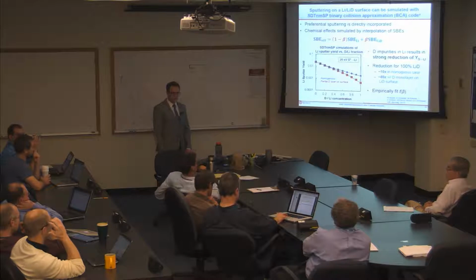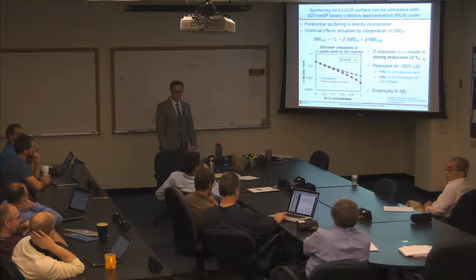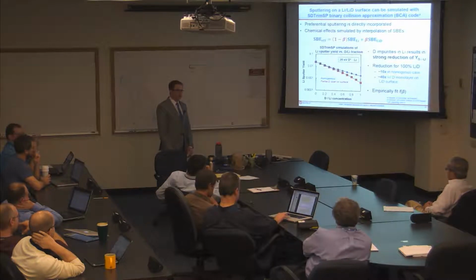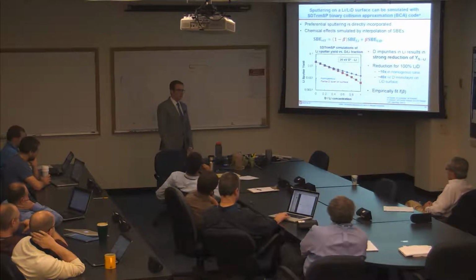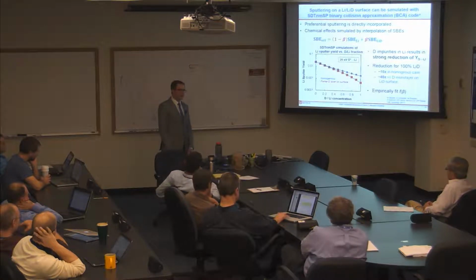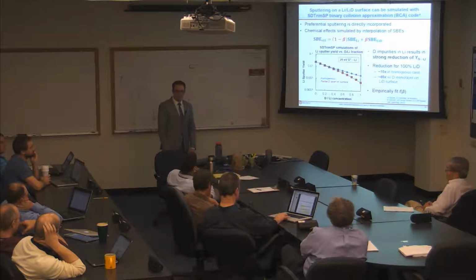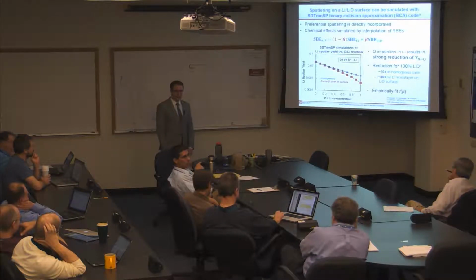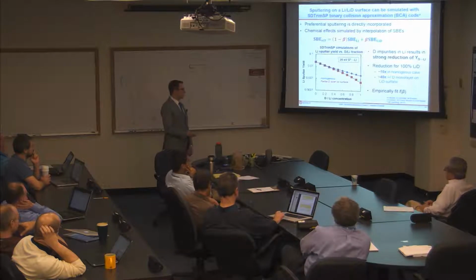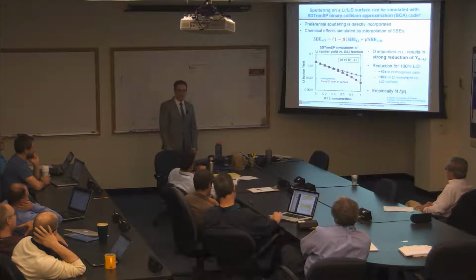You could have more D than that. But beta is 2. So in PISCES experiments, they found that the maximum deuterium concentration they ever saw retained in a liquid was 1-to-1. And they did thermal desorption spectroscopy on the liquid layer after the experiment. If you could go above 1, then in principle this model would predict even stronger reductions of the sputtering yields. But experiments have suggested that that can't happen.